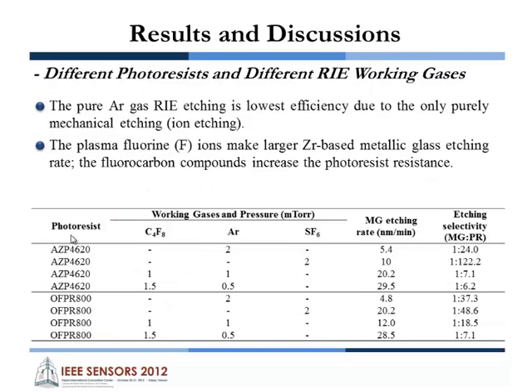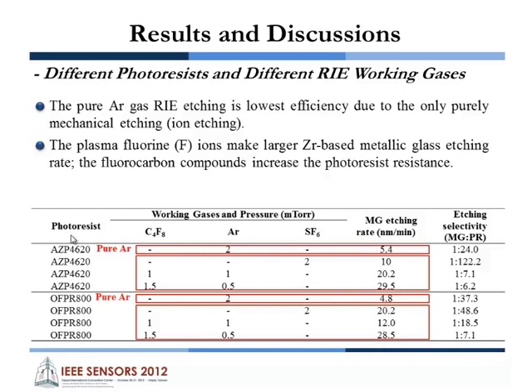For this page, we also tried different photoresists and different RIE working gases during the RIE etching. Two kinds of photoresist are shown here, and there are three kinds of working gas: C4F8, argon, and SF6. Firstly, from the metallic glass etching rate, we can see pure argon is the lowest compared with the others, because pure argon only has ion etching without chemical etching, and these two have fluorine ions, so they have chemical etching in them and the etching rate increases.